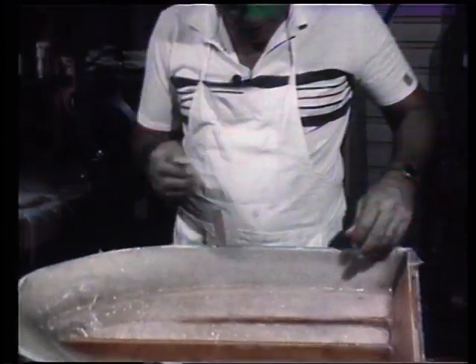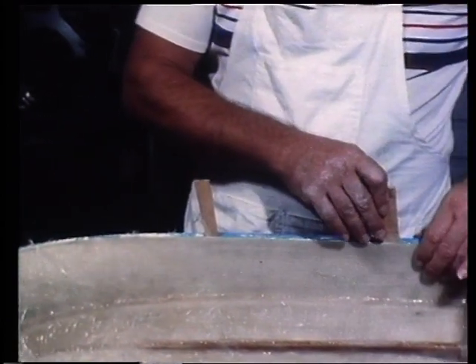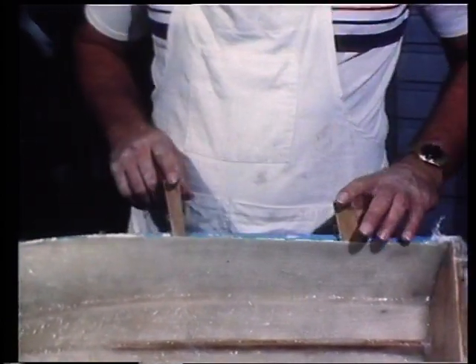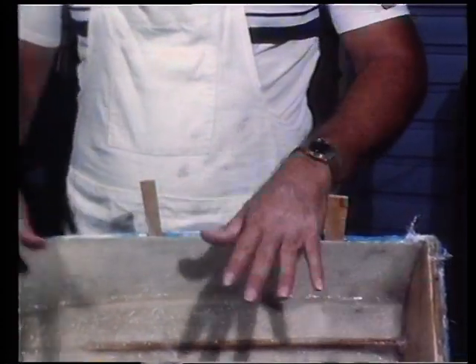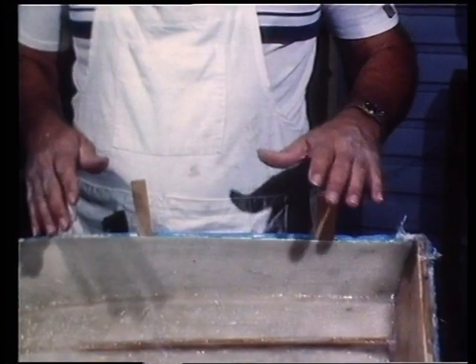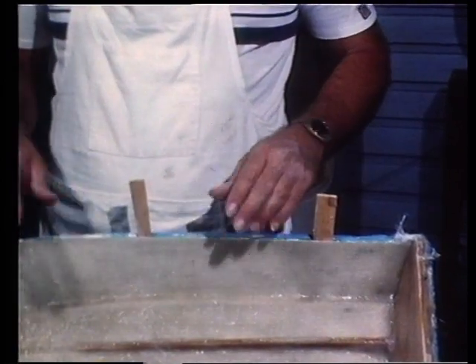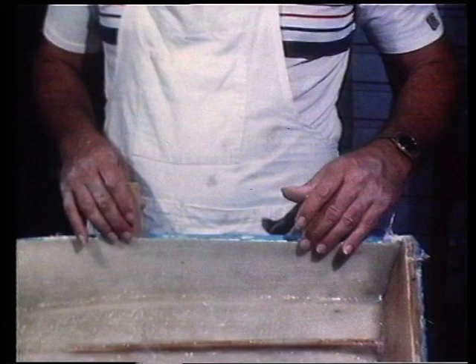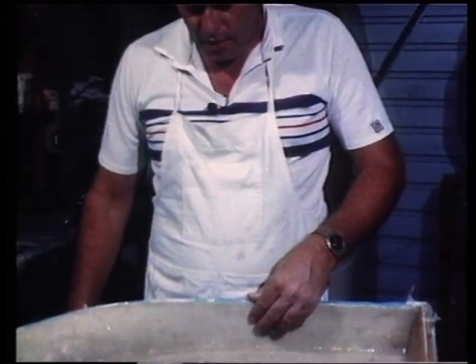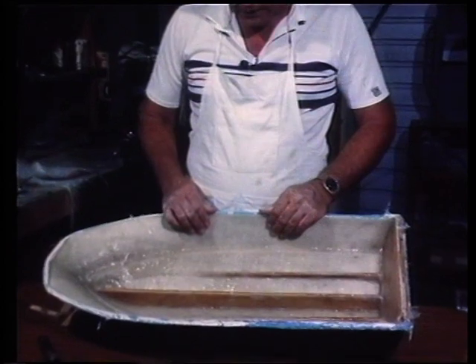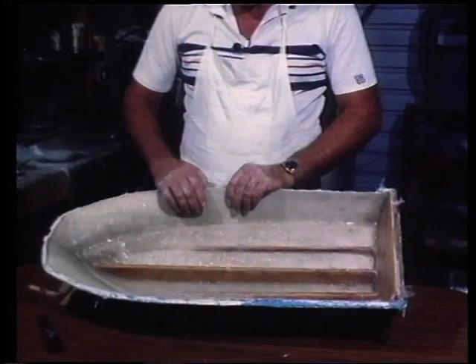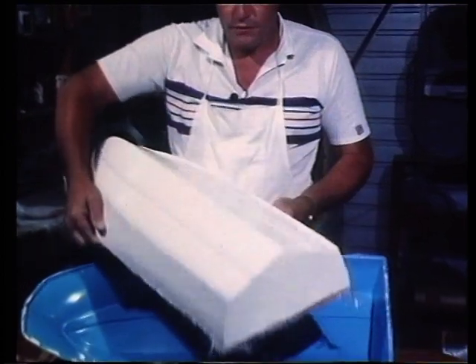Now you'll find that as you go you can hear it cracking and popping as it releases from the mould. You may have to tap them with a hammer, but whatever you do, don't touch any other area of the boat or the mould with the hammer, and if you're patient and careful, you'll find that they will always pop out, providing of course that you've followed the instructions at the beginning of all of this and put the right sort of release system in. So we'll assume that we've done all that, we've popped it out, it is now released, and it's come up above the mould surface. It really is just a matter then of lifting it out like that, and there is the finished product.